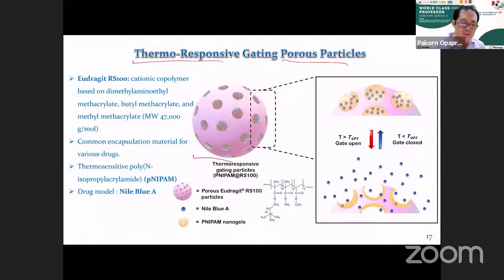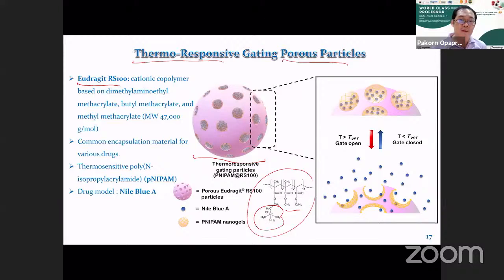The porous material here is prepared from a material called Eudragit RS100, which is a cationic copolymer that contains positive charge and also acrylate groups. So we can make this into porous particles like this by using a common technique. And then we show the performance of this particle by encapsulating a drug model.